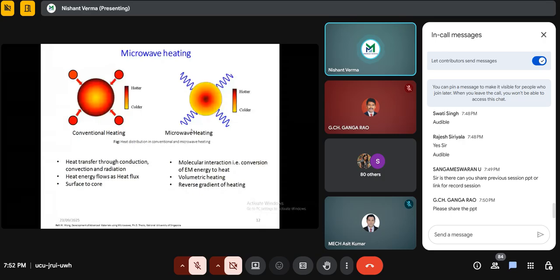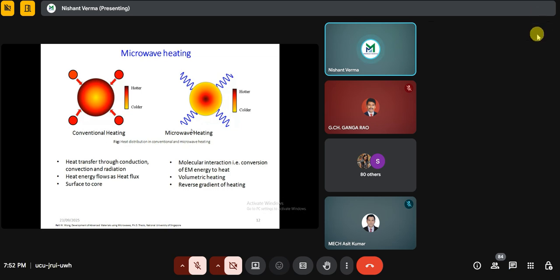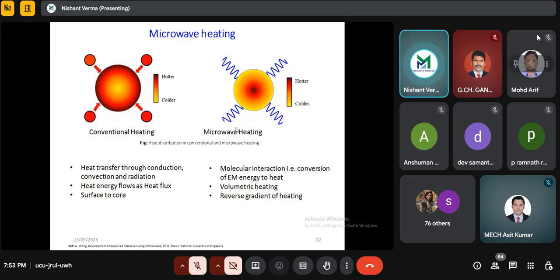I would not explain the conventional technique. This technique I would explain. In case of conventional heating and microwave heating, both the heating procedure and heating mechanism are different. In conventional heating, the heat transfer occurs from surface to core. Most of the time you have observed that suppose you have kept a container of water on the stove. Sometimes you observe that the upper layer of that water is hot, and the lower bottom layer water is cold. How does this happen? This happens because of the thermal gradient, and the heat transfer from hotter region to colder region. This is the conventional heat transfer phenomenon.